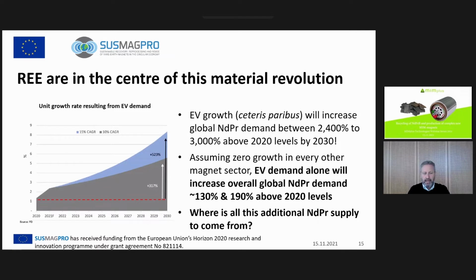And if you now look at average growth rates of 10 to 15%, you know, before I've shown you 20, this leads to enormous numbers. So that means that the increase between 20 and 30, if you assume nothing else is changing, is between 2,400 and 3,000 percent. And assuming zero growth in all other magnet-containing sectors like the wind turbines and so on, the demand growth of neodymium and praseodymium rare earths is between 130 and 190% above the 2020 levels. Of course, always assuming this 10 and 15% growth. And the question is now, where is all this additional neodymium and praseodymium supply coming from?